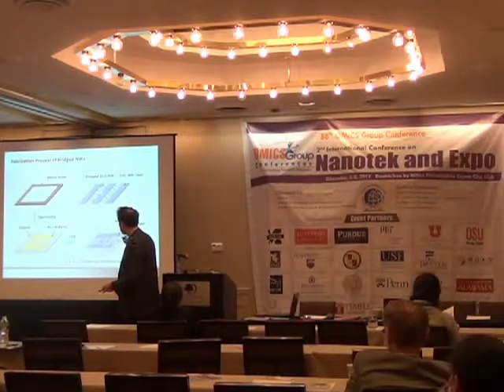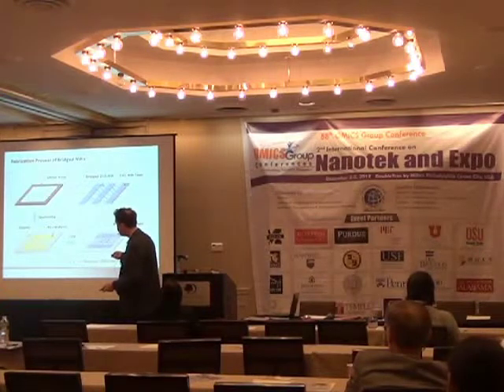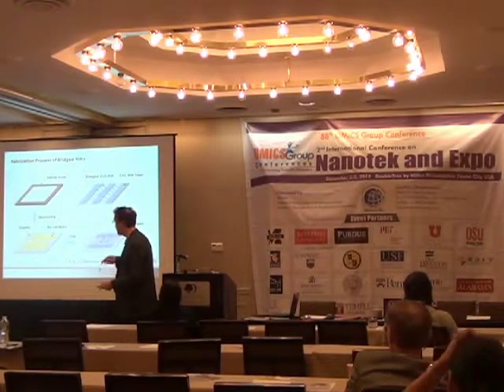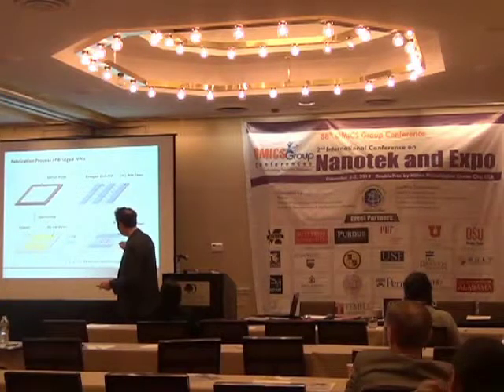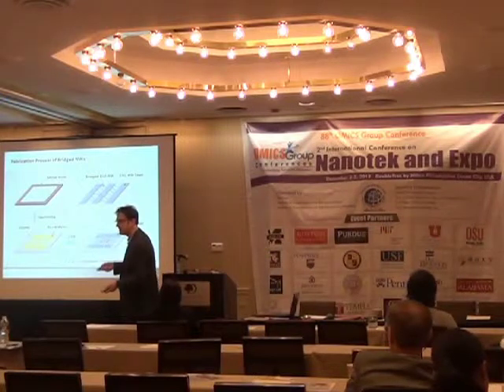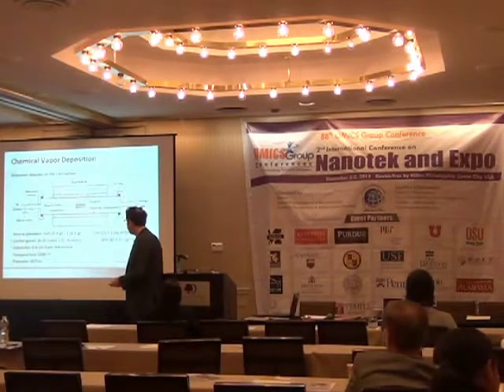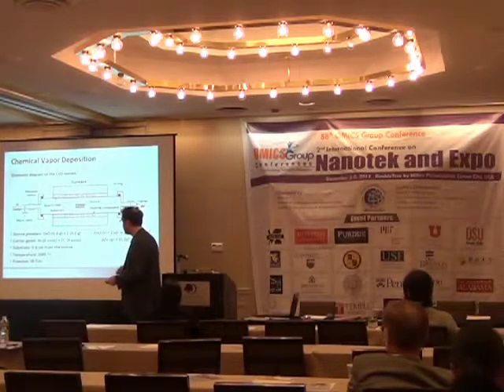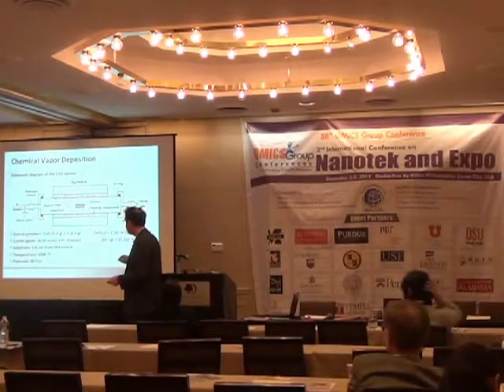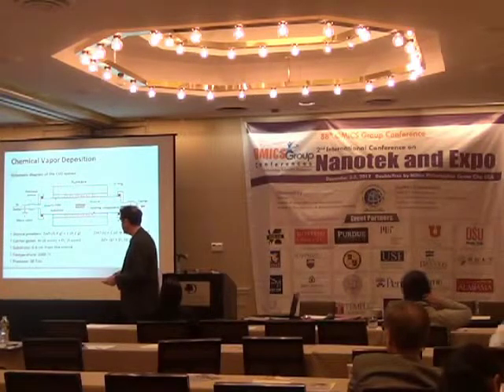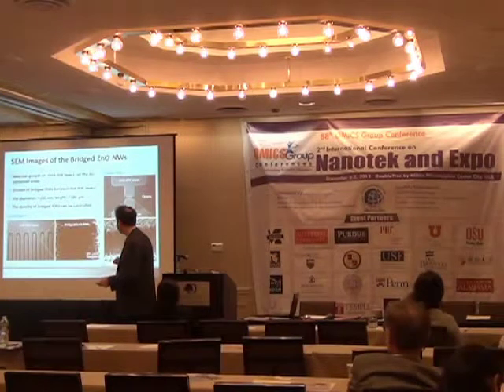And then we grow these nanowires. We have a large growth on the gold, and we just have to select the growth parameters to obtain very long nanowires, because the gap is 100 micrometers here, and randomly some of the nanowires will reach from this electrode to the next. That's as simple as that. The furnace that we use is a very standard one. We just feed zinc oxide powder and form a vapor that is made to react on this substrate with oxygen flow.